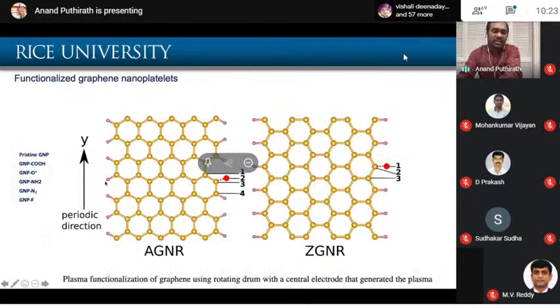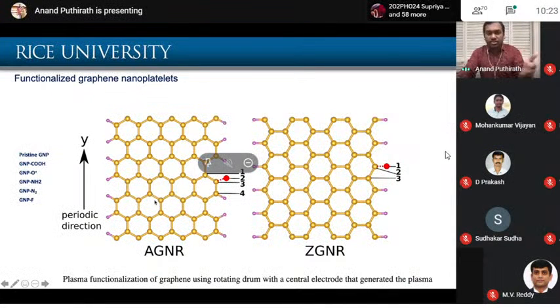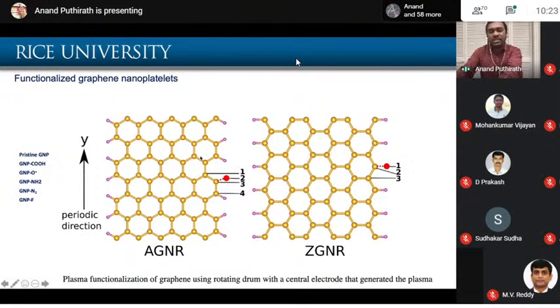So we gently functionalize, because if you functionalize with what you call a heavy acid kind of medium, it will break several things, right? And we never know, some basal planes, atom vacancies, those things, and so to study the actual variation, probably we need to functionalize gently. So we used a plasma type of approach to functionalize it, so that the whole structure will stay intact and impurity levels will be very low.